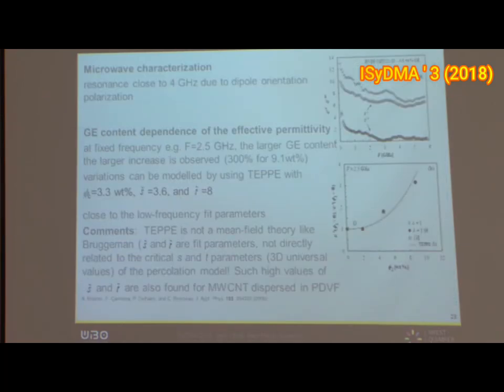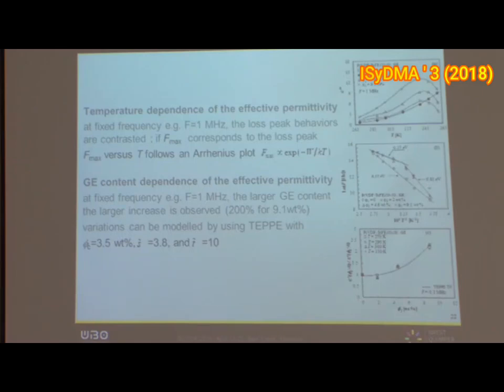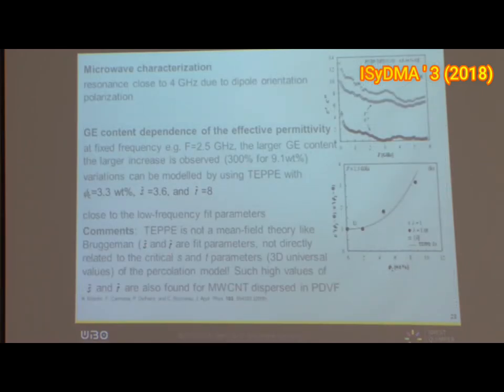When you do the same measurement at microwave frequency, you get spectra which are pretty complicated to understand. But when you look at the graphene content, you can fit with the same TEPPE equation, with exactly the same parameters: percolation threshold, and S and T parameters, with some uncertainty value of course.